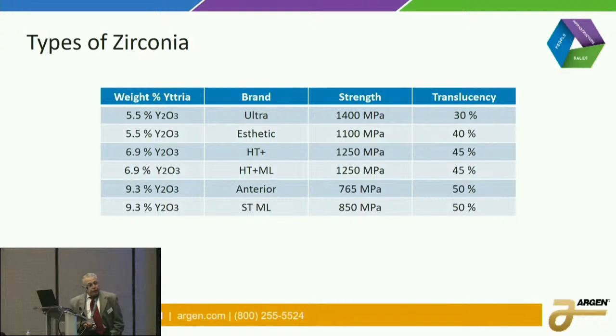Now, as I said, there are different types of zirconia. The first ones were like 5.5% yttria, and those were the high-strength types like Zircon. I'm using our Argon brand here, Ultra. That had a very high strength because it was being used in thin wall sections. You only had 4/10 or 5/10 of wall that you're going to bake porcelain on. But the translucency was poor, less than 30%. And then full contour zirconia came out, and in our case, we marketed it as aesthetic, and that only had a strength of like 1,100 megapascals, but the translucency was much higher.